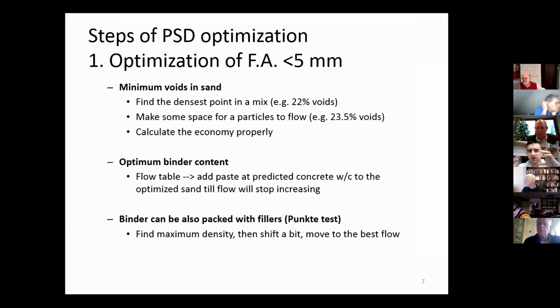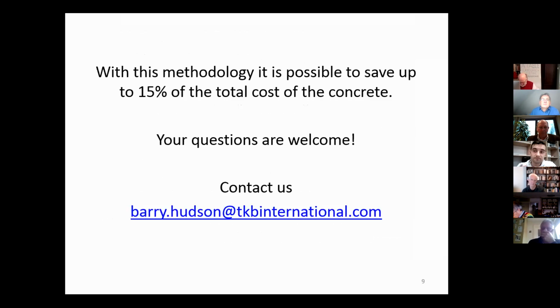Firstly, we optimize the fine aggregate and the binder, and then we optimize the coarse aggregate voids content separately. You can also use this methodology, so-called Puntke test, to optimize the granulometry inside the binder. And then you put three parts together in the best proportion to have less cement, less CO2, more cost efficient, and that's all. So usually if the rheology is better, the compressive strength is also higher.